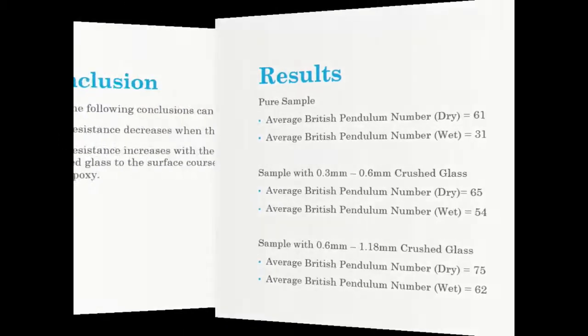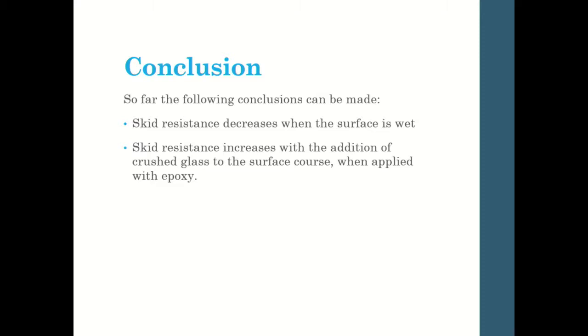So from this, I was able to conclude that yes, skid resistance does in fact decrease when the surface is wet, and when you add crushed glass to the surface using epoxy, it does improve the skid resistance of that surface. Now, I specify epoxy because I'm also exploring other methods.